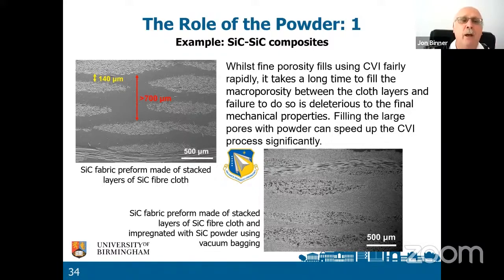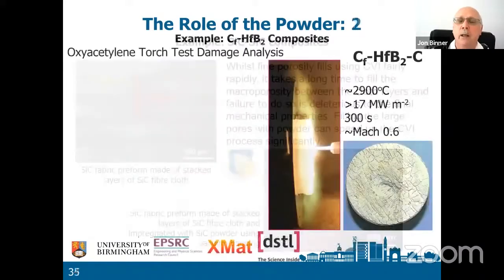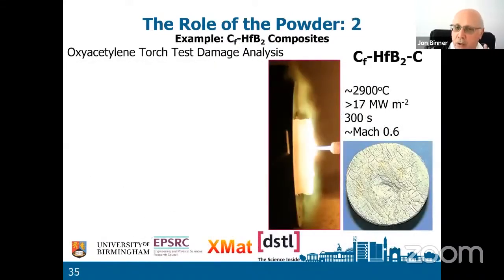So that top left figure, you've got quite large voids. This is a micro CT, up to 700 microns in size. And that's quite a big void. We can fill them with the powder, so that helps nicely. In the carbon fiber ultra high temperature ceramic system, it's quite different.